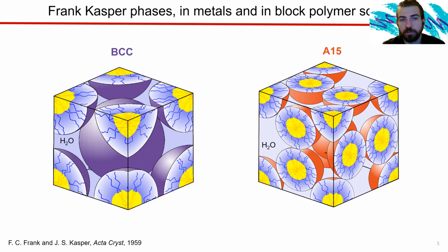Now, on the left, we have a body center cubic phase. On the right, we have a Frank-Kasper A15 phase. Now, at first, this looks kind of complicated. Let me pull up my laser pointer. At first, this looks complicated, but if you look closer, you can see that the A15 phase is actually just a body center cubic lattice where you have a micelle in the middle and one at each corner. But in the A15 phase, you also have these two micelles on each face of the unit cell. So you could imagine that this would be a little bit more brittle than the body center cubic phase, just because there's less sliding planes, it's more compact, there's more going on in one unit cell.